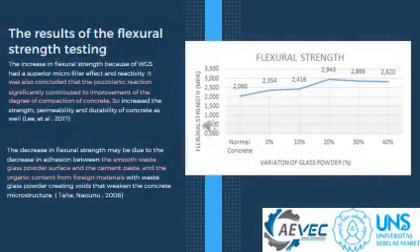And this is the result of the flexural strength testing. Flexural strength increases in variation of 0 until 20% glass powder and decreases in variation of 30 and 40% glass powder.